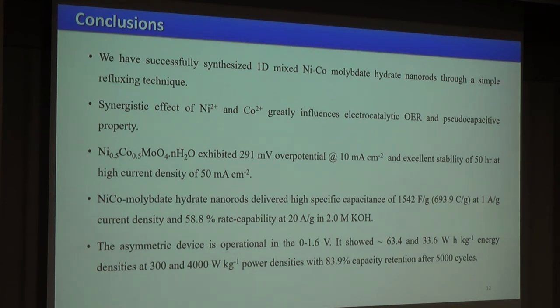And further, this material also exhibited promising energy storage activity as a positive electrode material, and the final asymmetric device shows good capacity retention after 5000 cycles and also considerable energy density at a high power density.